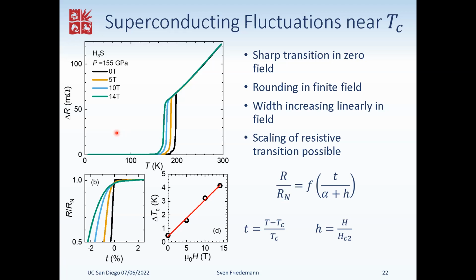I could easily imagine that it sublimates or dissociates into hydrogen and sulfur, for instance, and I don't see what would hold it from doing that. I mean, of course, we are using diamonds in these cells, which itself is a metastable state, which is stable at ambient pressure, at ambient conditions. But there's a big difference in that the bonds of diamond are very strong, and it's an insulator. It's well away from the chemical potential.